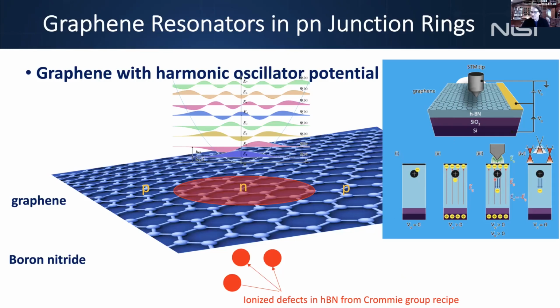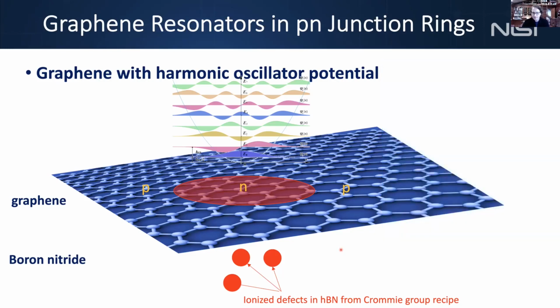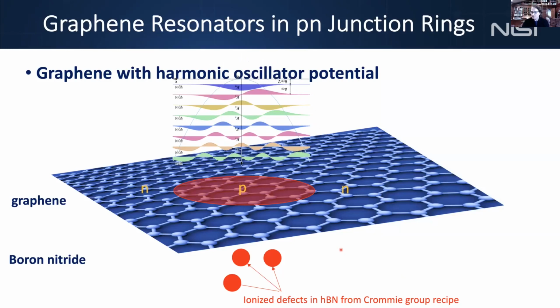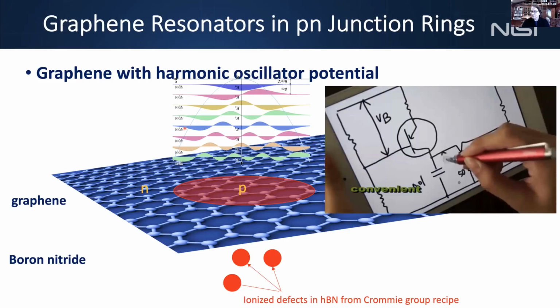And the direction of the polarization depends on the sign of the gate voltage, which you had active during the pulse. So you can create a PNP junction, as you're shown here, or if I switch the polarity of the gate voltage during the pulse, I can create an NPN junction, where the harmonic oscillator potential is concave this way. And for these measurements, I'm going to show you a p-doped quantum dot where the potential is in this direction. So this is a very general method where you can essentially use the probe tip to write any kind of doping pattern. We've written, for example, multiple quantum dots this way. But for today's talk, I'm just going to show you one dot.